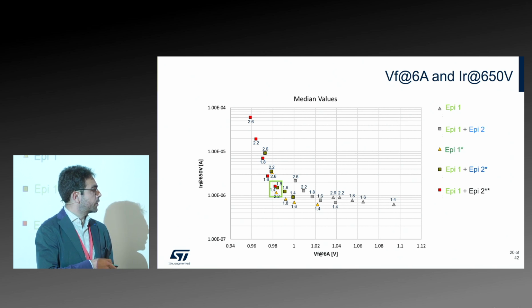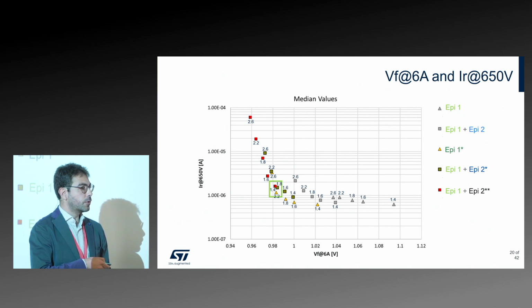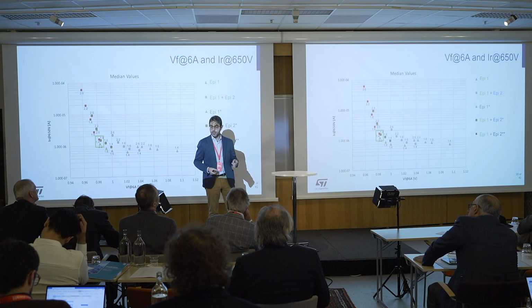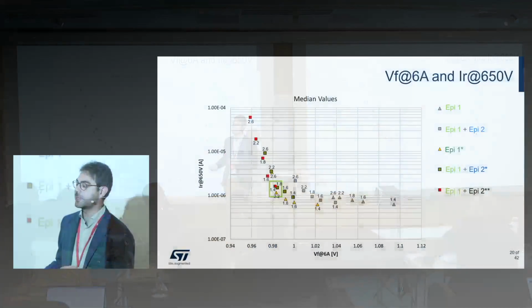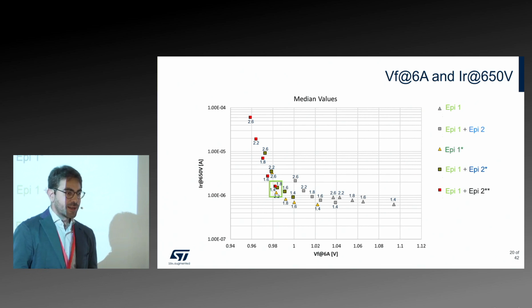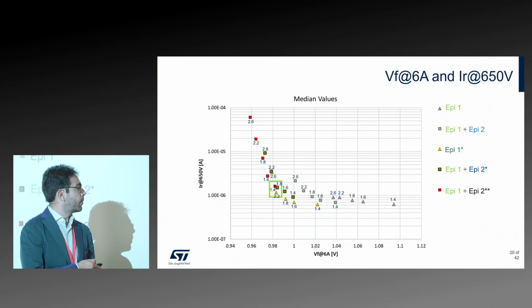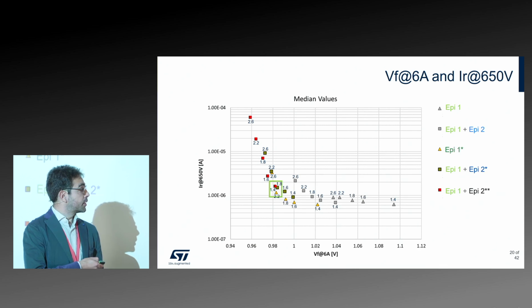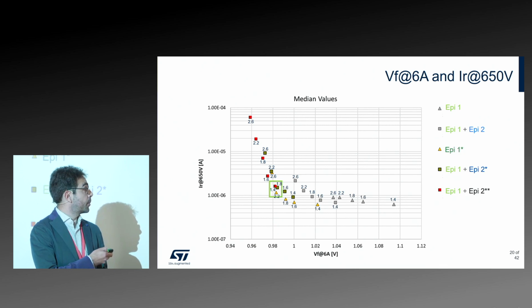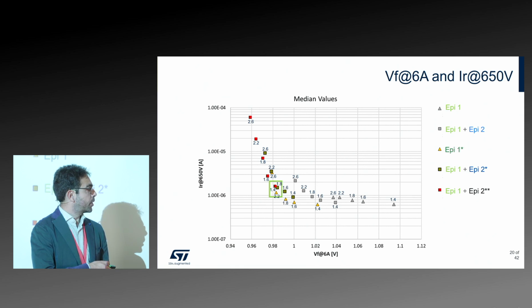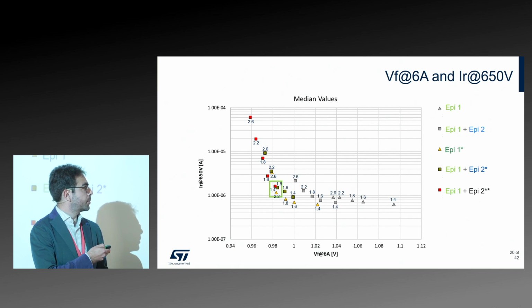And from this point to this point, we observe a very nice curve in which we can find all these points. This means that when marketing says that every time I have to be the best in leakage and VF, but this is not the case. If I would like to find a compromise, this to me is really interesting because I can continuously span from the optimization of the leakage to the optimization of the VF.